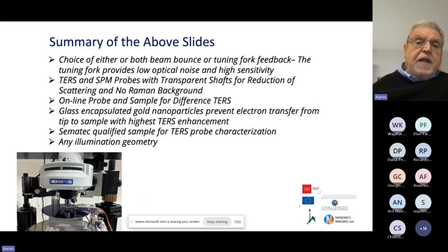So this is a summary of the above slides. A choice of either beam bounce or tuning fork, with the tuning fork having certain advantages. TERS and SPM probes with transparent shafts for reduction of scattering and no Raman background. Online probe and sample for different TERS. Glass encapsulated gold nanoparticle preventing electron transfer from the tip to the sample with highest TERS enhancement. Sematec qualified samples for TERS probe characterization. And any illumination geometry. Some people, I won't go into why, like side illumination because they can get some polarizations that you cannot, a Z polarization, which really is not necessary. But anyway, that's another story.